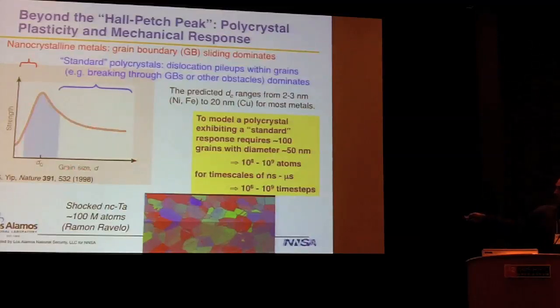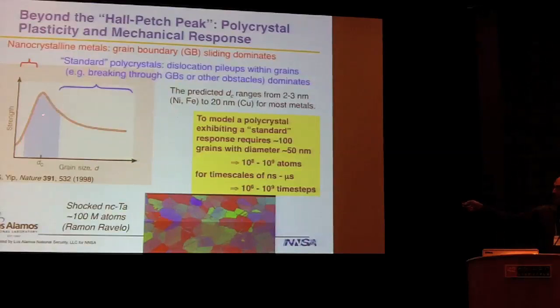It's long been known that as the grain size in the material decreases, the material's strength goes up. But this can't continue forever. Eventually, as you get down to a grain size of 1 atom, you don't have a crystal structure, you have an amorphous material, and it has a much lower strength. So there's some turnover region here. This is actually a very popular topic in materials science, this nanoscale Hall-Petch turnover effects.